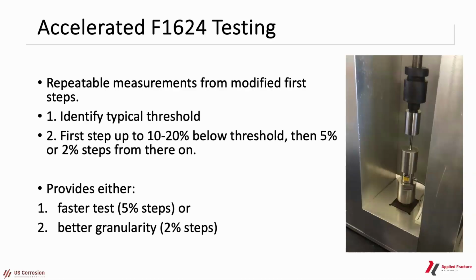And then the last one is the accelerated testing. So it's already an accelerated test, but for quality control purposes, you can determine a material and determine the initial threshold by doing your testing. And then say, for example, let's say you determine 70% as an acceptable threshold for you. We've been doing research to show that if you do your initial loading correctly, you can jump up to within 10 or 20% of that threshold and then start doing your step loading and cut down the amount of time substantially further. So what that means is instead of the test taking 20 hours, you might be able to complete it in 6 to 8 hours. And that's perfect for industrial production because you want to be able to have answers the same day or next day. So by the time you're finished making a part, it's ready to go out the door.